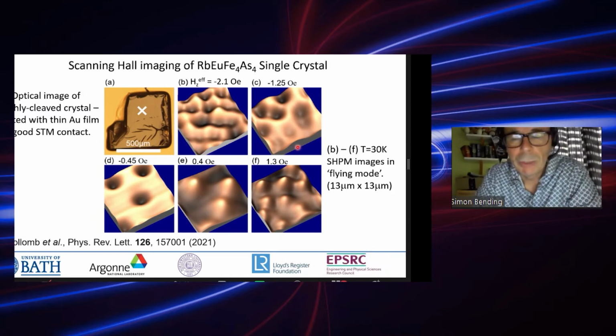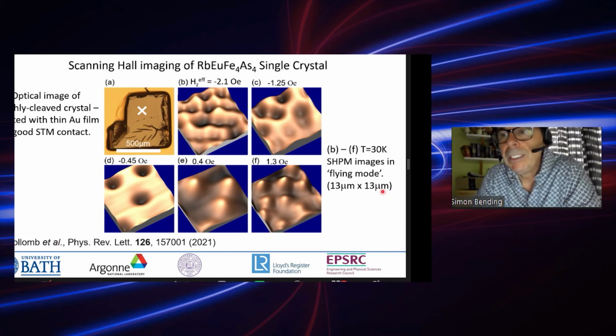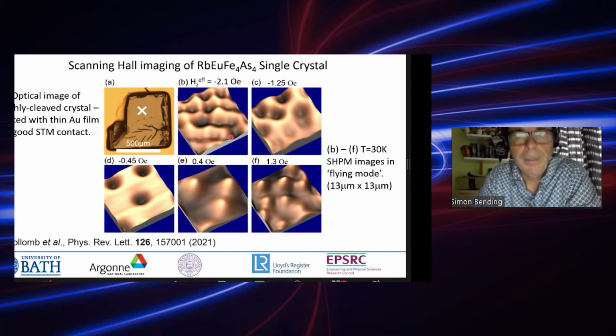If we take our measurements, then these were all in different field-cooled fields. These are negative fields here initially, then we go through 0 to go to positive fields. You can see in negative fields, we see these black vortices here. As we go positive, they revert to white vortices, as you would expect. Because we're working at quite low temperatures, the scanning areas are quite small. The piezoelectric coefficient of our scanner shrinks with temperature, and these are about 13 microns by 13 microns inside.